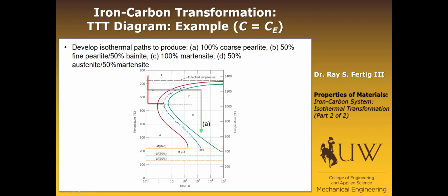Now we want to take the remaining austenite and convert it to bainite. That means we have to rapid cool to, let's say, 500 degrees and then completely transform the remaining austenite to bainite. So we rapidly cool back to 500 degrees and reset the time, and then we hold long enough, in this case 10 seconds, so that the remaining austenite gets converted to 100% bainite, and we end up with a 50-50 microstructure of fine pearlite and bainite.